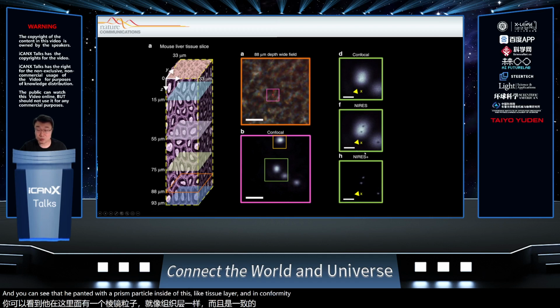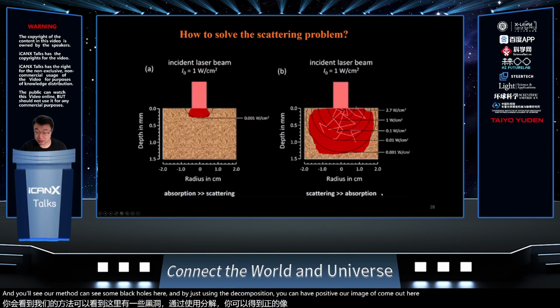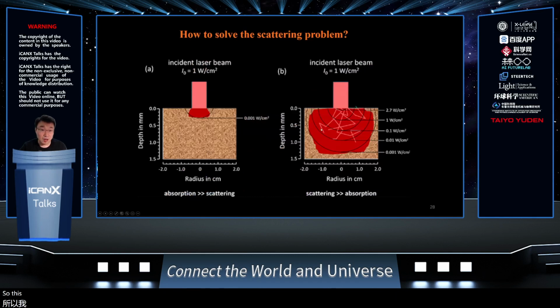And you can see that if we put some particles inside this tissue layer, in confocal you couldn't resolve them. By using our method, you can see some black holes here. And by just using deconvolution, you get the positive image here. So this is how we can solve this scattering problem.